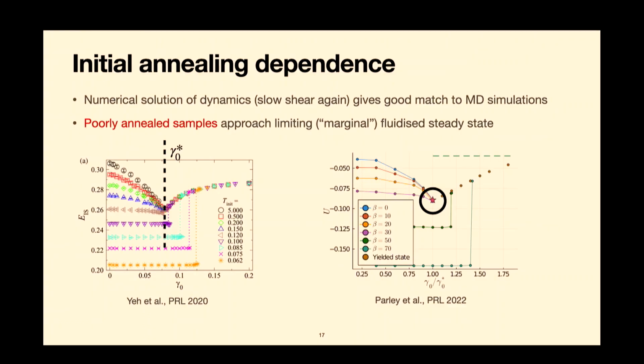Okay. So let's focus first on the poorly annealed samples. What I'm showing you on the right here is basically the analog of this simulation plot on the left. We can do the same thing with our mean field model. We run the dynamics through a number of cycles of shear until we reach steady state. Then we record, in this case, the energy as a function of the strain in this steady state that we've reached. And you see for these poorly annealed samples, which are these top curves here, this looks very similar to what we have in the simulations.